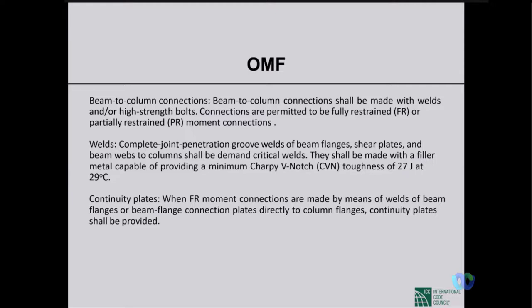Beam to column connections shall be made with welds or high strength bolts. Connections are permitted to be fully restrained or partially restrained. So even for seismic case, partial moment connections are allowed for OMF. Welds, complete joint penetration groove welds of beam flanges, shear plates and beam webs to columns shall be demand critical welds. They shall be made with a filler metal capable of providing a minimum Charpy V-notch toughness of 27 joule at minus 29 degrees centigrade. A little bit different. Previously, we talked about 27 joule at minus 18 degrees centigrade. This is 27 joule at minus 29 degrees centigrade. So when we provide filler material of this toughness, that is called demand critical welds.